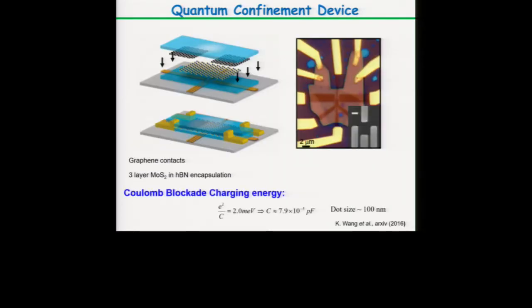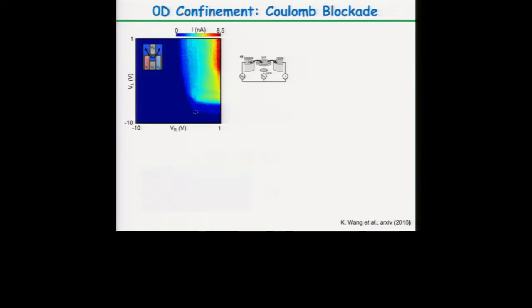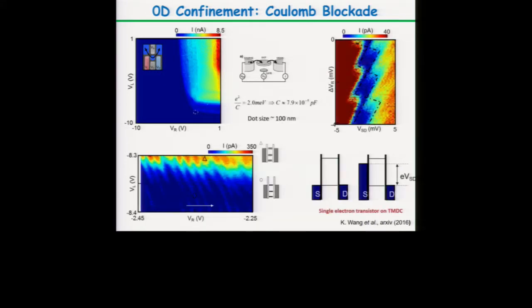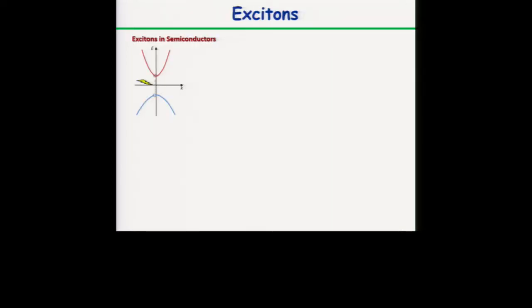Because of the good contacts, Ke Wang in our group was also able to use graphene, as I mentioned, for multiple layers to make quantum dots. I'm just going to put this slide and mention that we can have contacts and we can create these quantum dots on TMDCs, right? Ke Wang showed he can get Coulomb blockade on 3 layers of MoS2 with these graphene contacts. I don't know if Ke is around, but he could explain it better if he's around. I will show later why that is important.